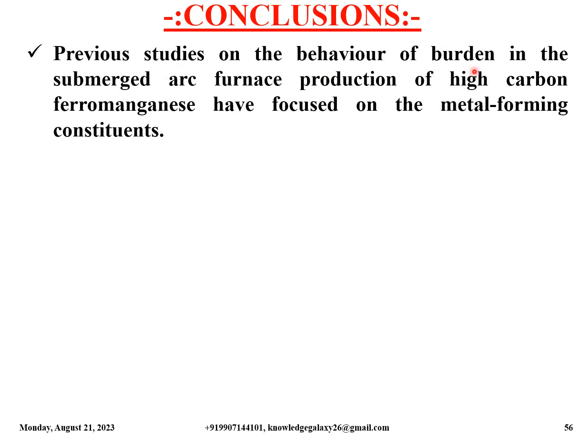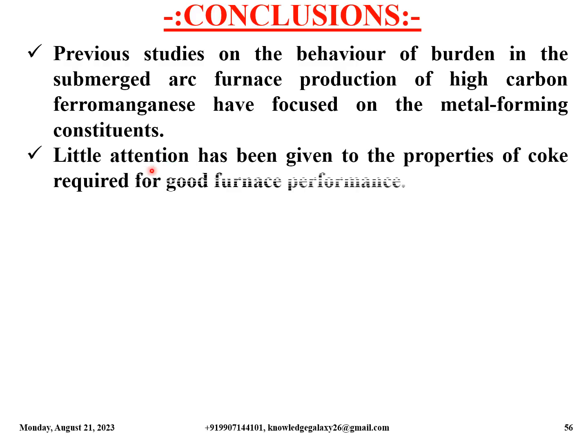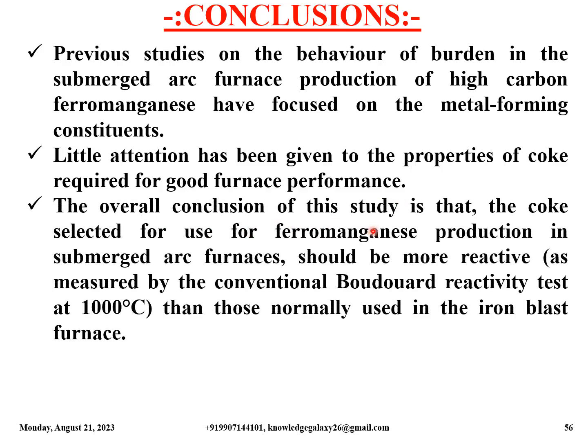So now let us come to conclusions. Previous studies on the behavior of burden in the submerged arc furnace production of high carbon ferromanganese have focused on the metal forming constituents. Little attention has been given to the properties of the coke required for good furnace performance. The overall conclusion of this study is that the coke selected for use for ferromanganese production in submerged arc furnaces should be more reactive as measured by the conventional Boudouard reactivity test at 1000 degrees Celsius than those normally used in the iron blast furnace.